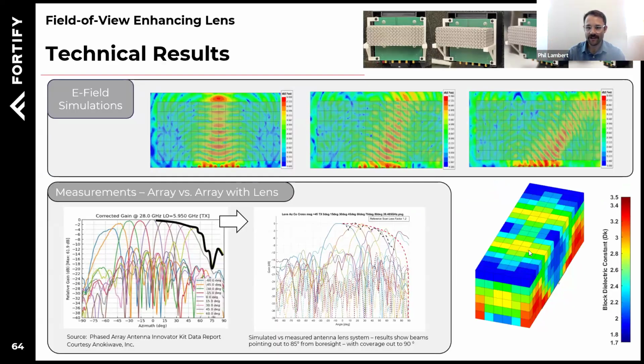Here's the distribution of that lens. In this example, we're only steering in azimuth. And so we only are looking at the azimuthal steering of this device. And you can see what those E-field simulations look like when the phase and amplitude are changed to create these beams that point out. So long as you have aperture at your most dramatic angle, you can create a lens that generates enough phase change to bend your beams to point out to 90 degrees. So you can see that happening here.